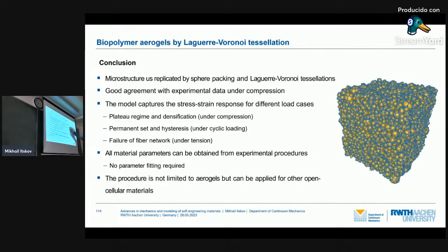You see here the spheres inside of these Voronoi cells. We try to describe this microstructure by sphere packing and Laguerre tessellations. We obtain good agreement with experimental data. We obtain good agreement also for the strain response, namely the plateau regime and densification are rather well described under compression. Permanent set and hysteresis are also described, and we can also describe the failure of the fiber network under tension.